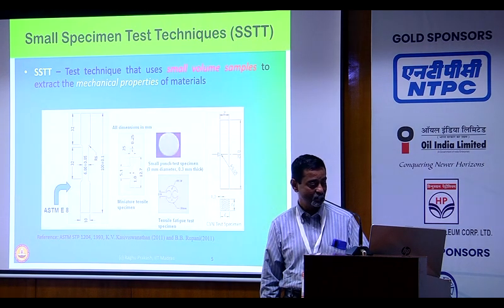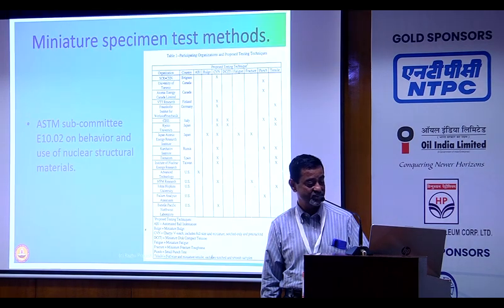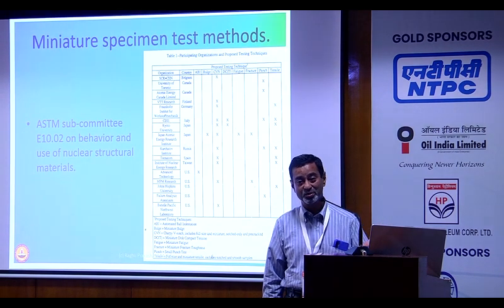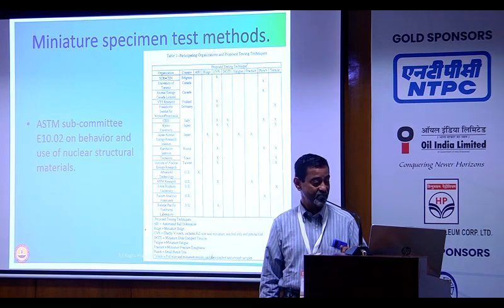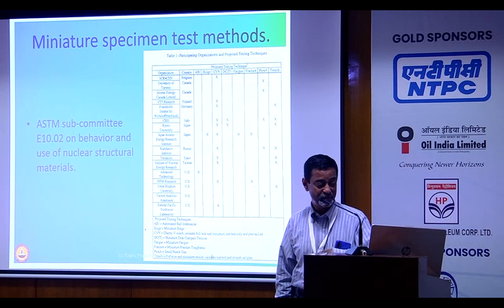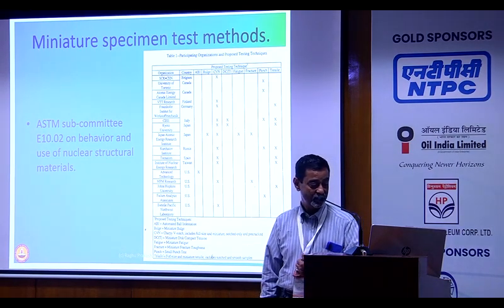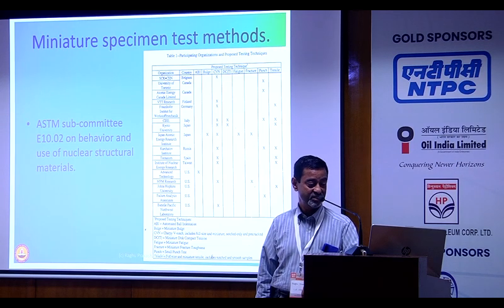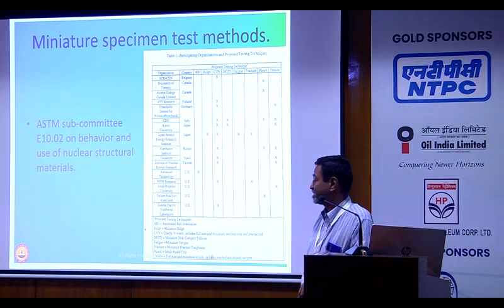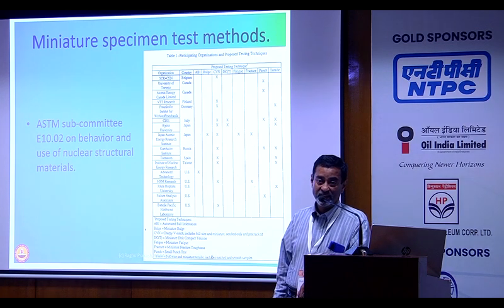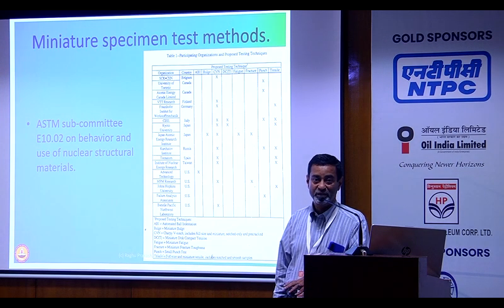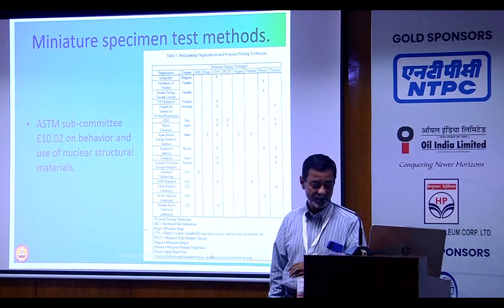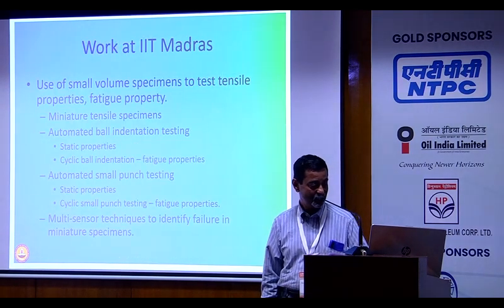So this is where we start looking at the effect of size scaling of these samples, because these allow us to go in situ, extract the samples and use them for future life predictions. So if you look at the ASTM subcommittee E10.02 on behavior and use of nuclear structural materials, they have summarized the different kinds of tests and which laboratories are working on them. And what caught my attention as a fatigue and fracture person is that not too many have worked in the areas of fatigue. So that's the reason why I started pinning my effort onto this.